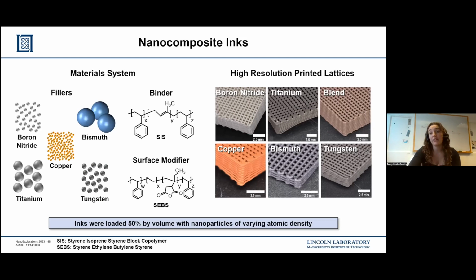We use a styrene-isoprene-styrene block copolymer, and that is then modified with something called SEBS, and we fill our inks with the nanoparticle filler 50% by volume. So that allows us to create these self-supporting high-resolution structures like these lattices. And as I said, these were printed out of a 250 micron nozzle tip.